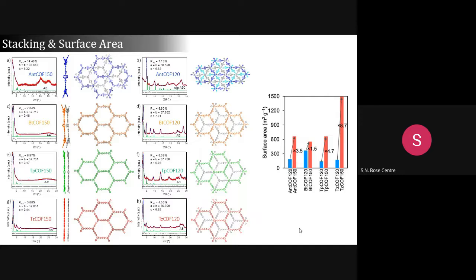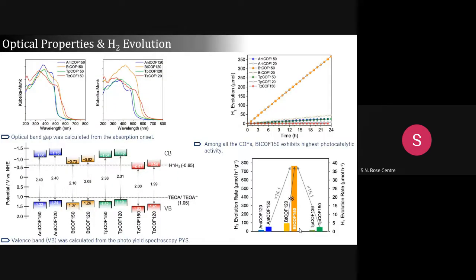For the other curve, we get AA packing at 150 degrees. You can see in all the cases AA packing, and at 120 degrees, we get the AB packing. Now, one question we asked on the first slide was how the packing affects the hydrogen evolution. The second question was how the porosity affects. Because we changed the packing, the porosity also changed. So here you can see the COF prepared at 120 degrees always has lower porosity than at 150 degrees. So although their band gap is similar, which I'm coming to in the next slide, their porosity is very different. Now we can understand from this how porosity is affecting the hydrogen evolution.